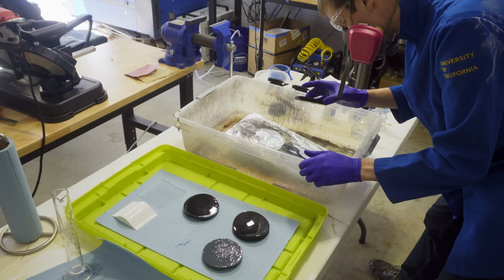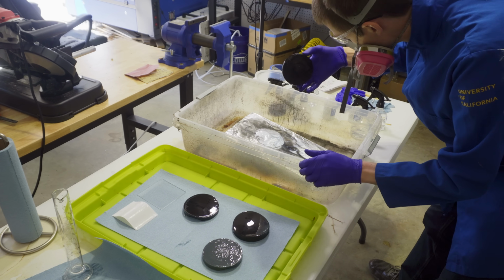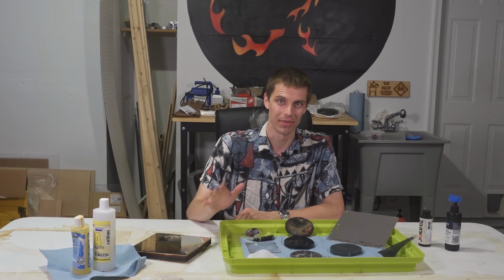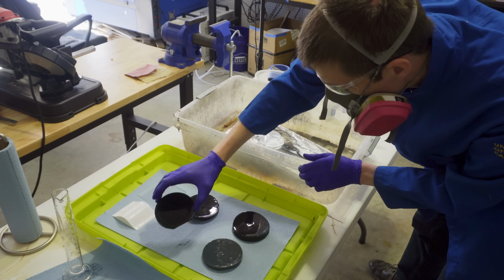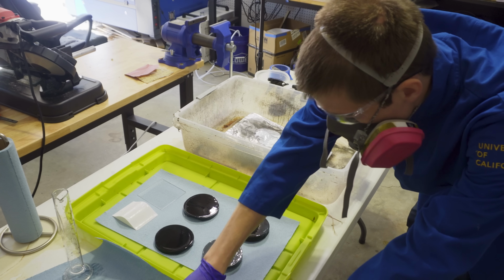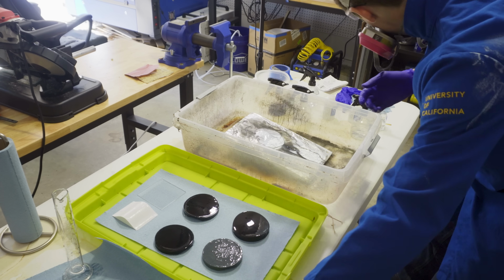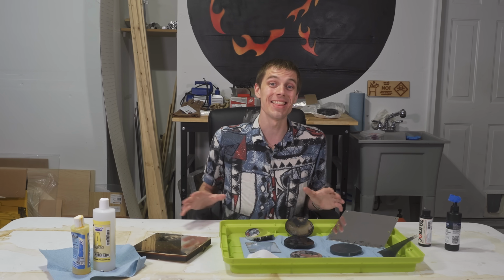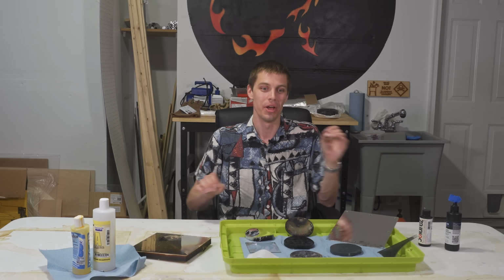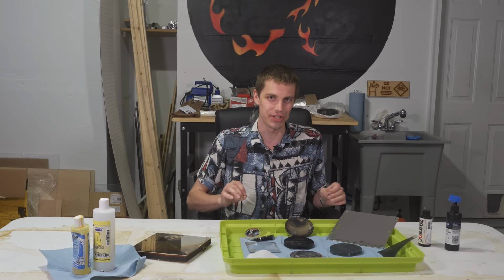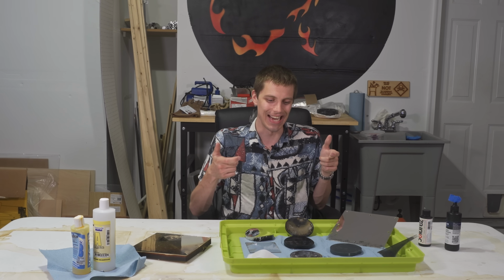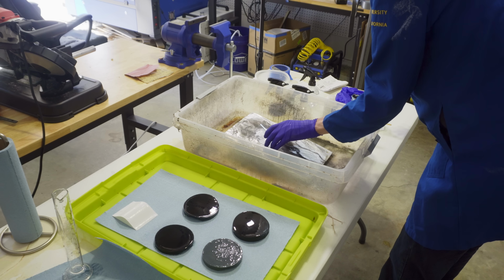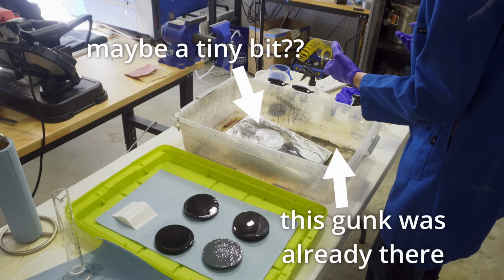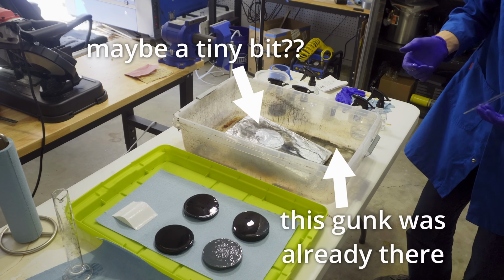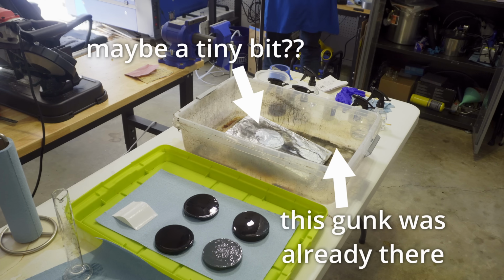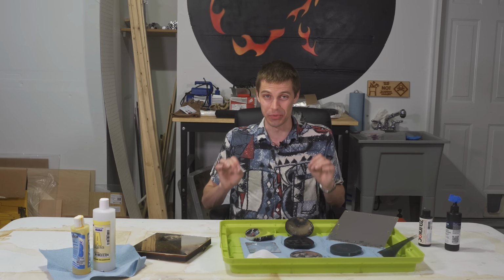The first time I tried this process again, it did not work. Well, crap. I want to blame the tap water. The first time I mixed these up, I diluted the solutions with regular tap water that is unfortunately full of ions, and once I redid it, I used distilled. I say that I would like to blame the tap water because the alternative is that I put the Part A solution in both of the spray bottles and there was no reaction actually happening. And considering that I didn't see a sludge of silver oxide in the basin when I was done, I fear that option two was more likely. I probably should not be let anywhere near a real chemistry lab.